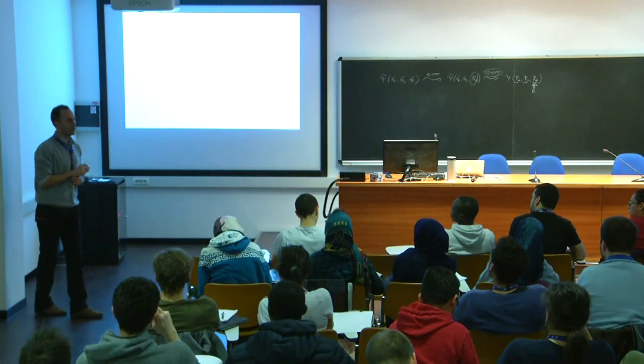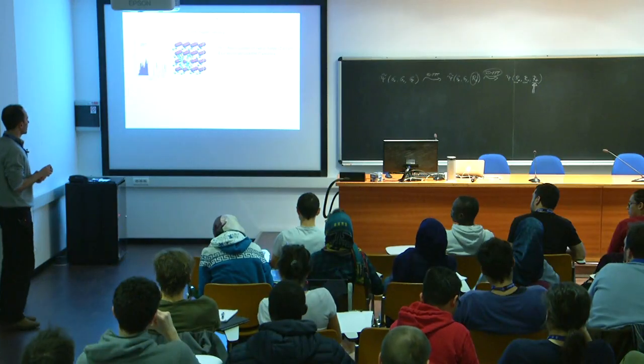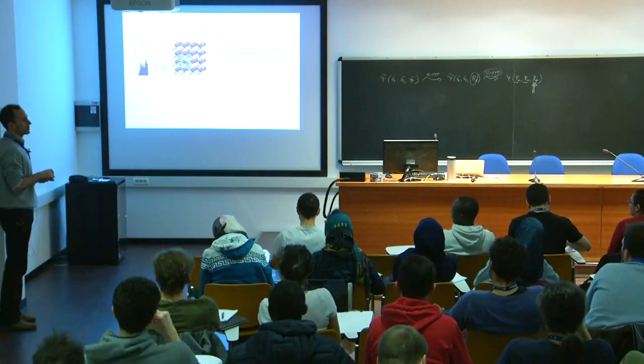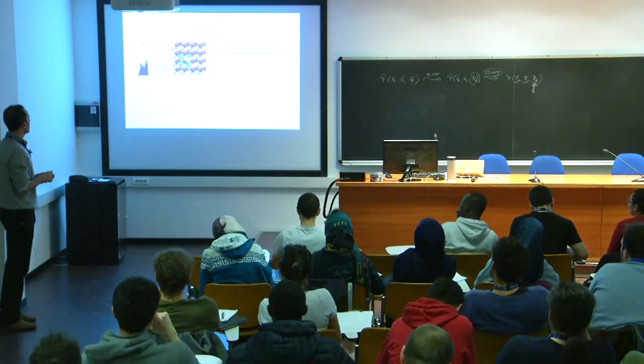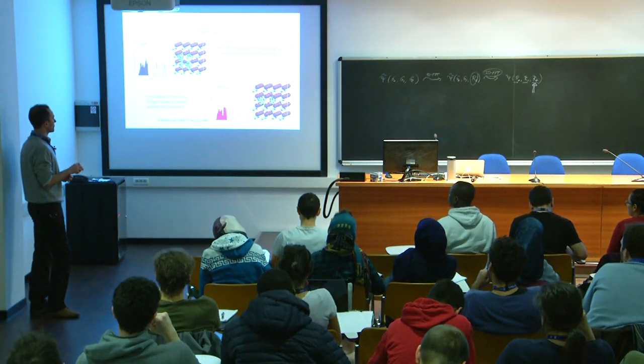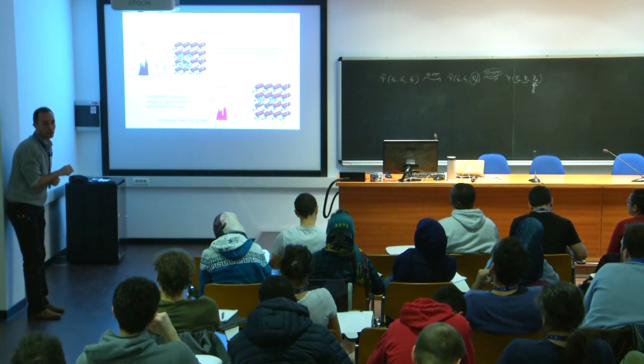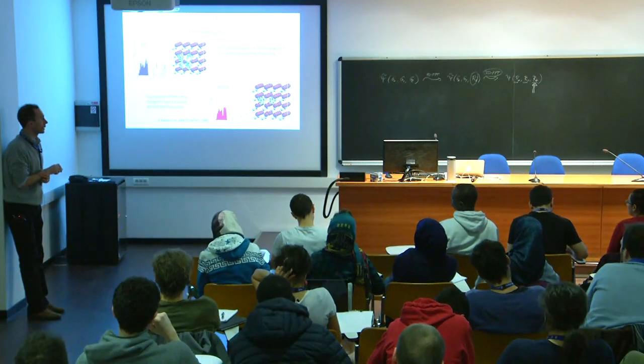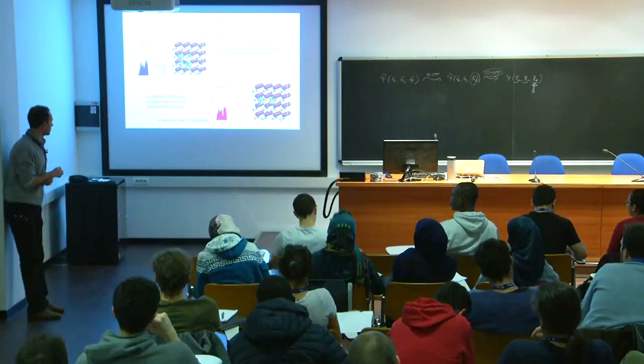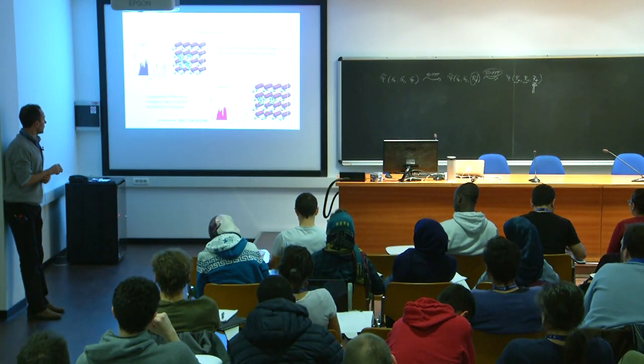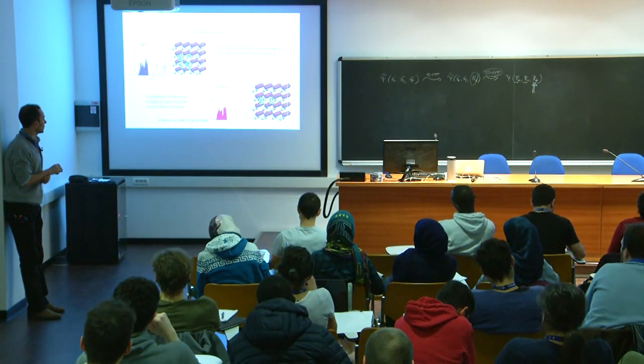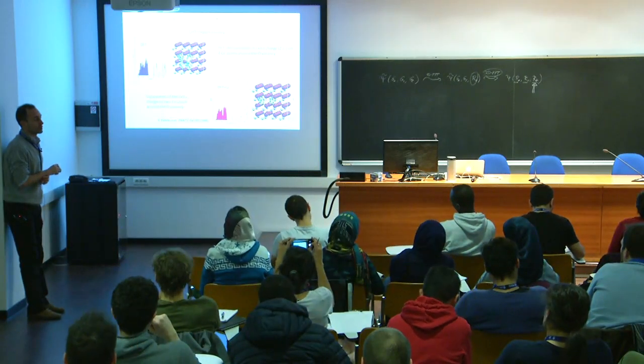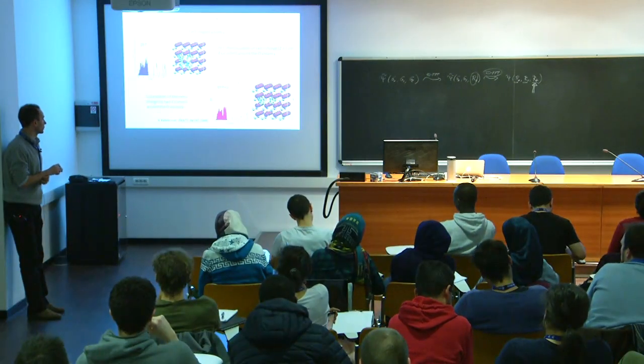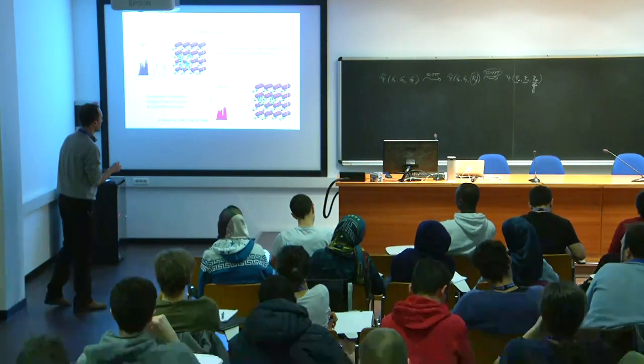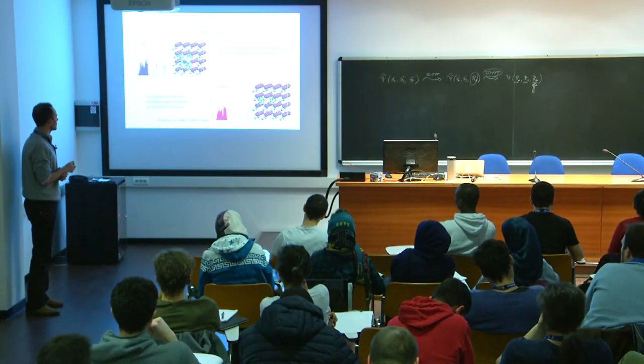Okay, how do the problematic cases I started with change with the use of this correction? So we started from this metallic delocalization of the extra charge around the defect, and now you get a localization, as you would expect, of the 2 electrons on 2 cerium atoms around the defect, the oxygen vacancy here. So that's described in this paper from 2005. And you see also that if you do the density of states, the electrons are localized in this gap state that forms because of the oxygen vacancy that you created in the structure.